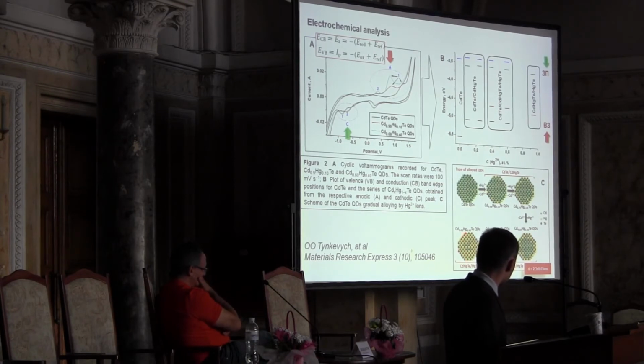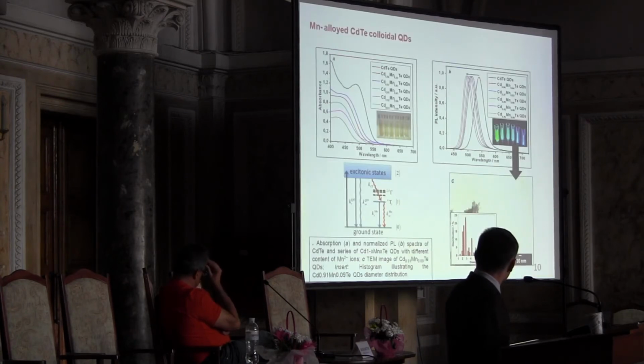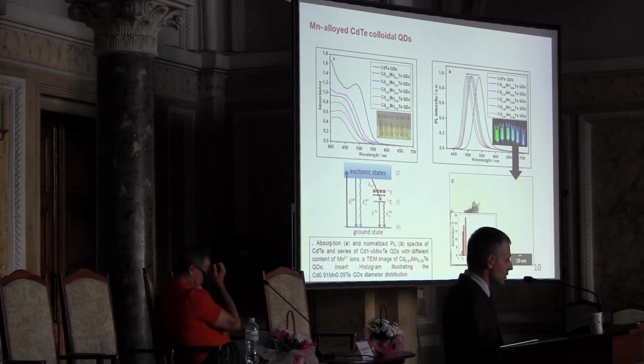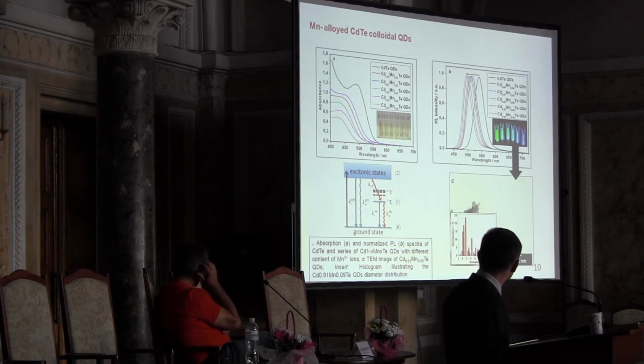So you have the mercury telluride on the top and some kind of core, which still contains a bit of cadmium. Well, this was the HgTe story, and it gives us the opportunity to shift luminescence to the infrared region. In order to shift it to the blue region, we tried to dope cadmium telluride with manganese.